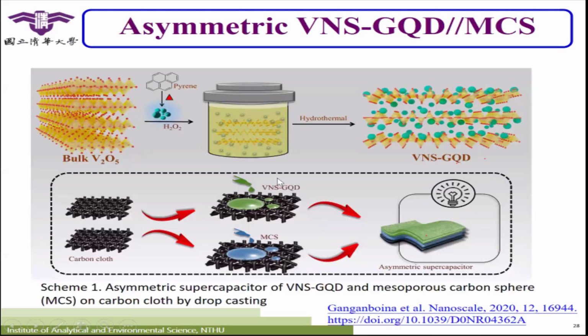That's the case. Not just for halloysite nanotube, you can still immobilize the GQD on the surface of two-dimensional materials, for example VNS here, vanadium oxide nanosheet. Here is the bulk V2O5. We try to use hydrothermal methods to separate the bulk V2O5 into single layers, and then we put the GQDs on the surface of our VNS. So we call it the VNS GQD. Here we do not use citric acid or some sugar. We use pyrene. The pyrene is quite easy to form GQD, and their surface area will be relatively high.